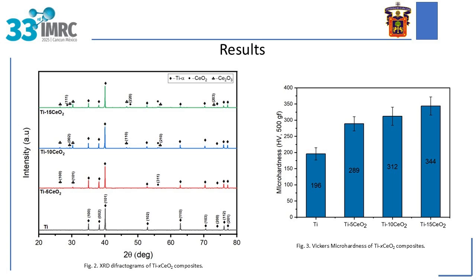The results of the XRD test aligned with the microstructure observed in the SEM images. The presence of titanium alpha phase is evident in all materials, and the phases of ceramic particles are discernible in the samples with ceria. The presence of peaks of cerium 4 oxide phase and cerium 3 oxide phase is observed, with the amount of the latter increasing as the ceria content in the material increases. This suggests that a phase transformation occurred in the ceria during the manufacturing process due to the high sintering temperatures.